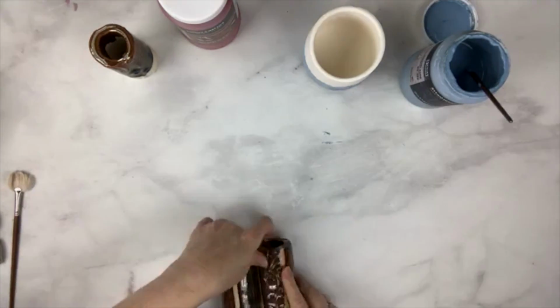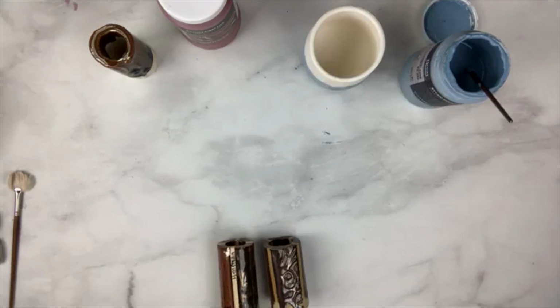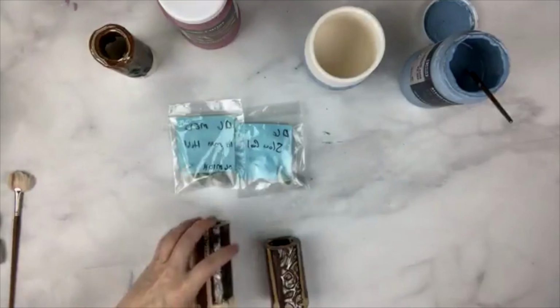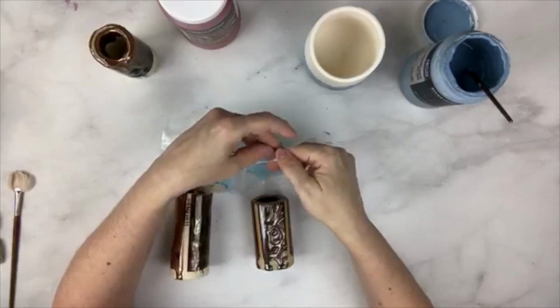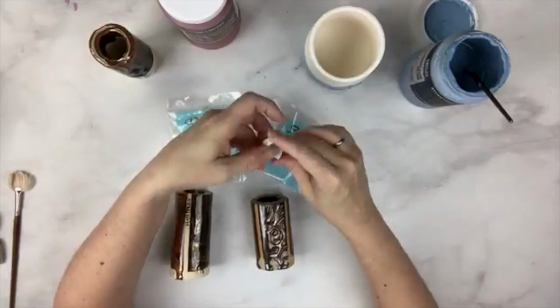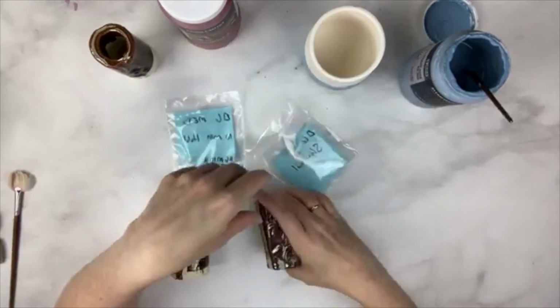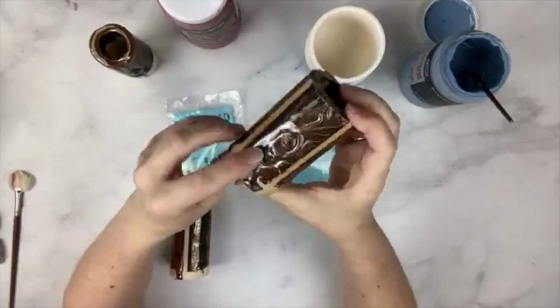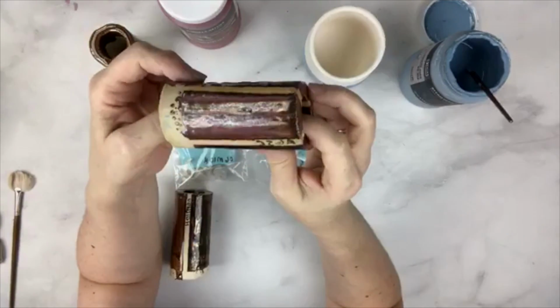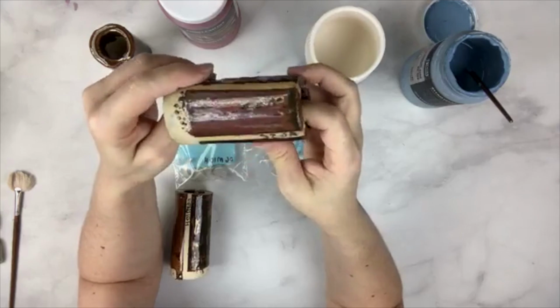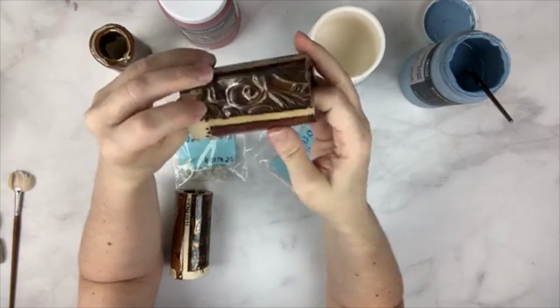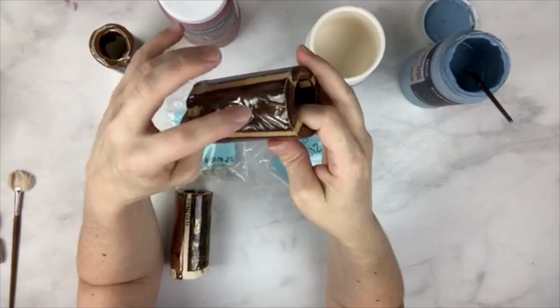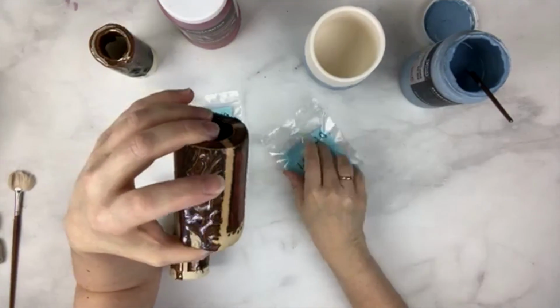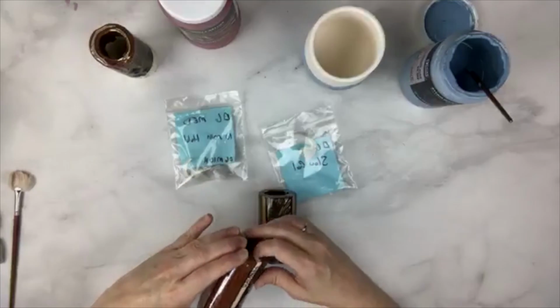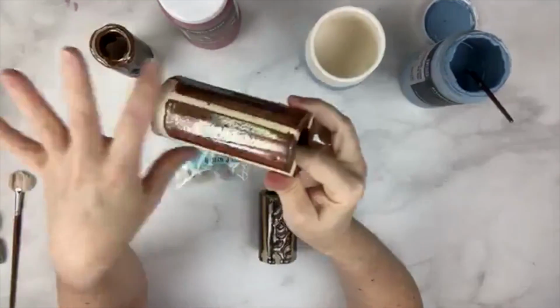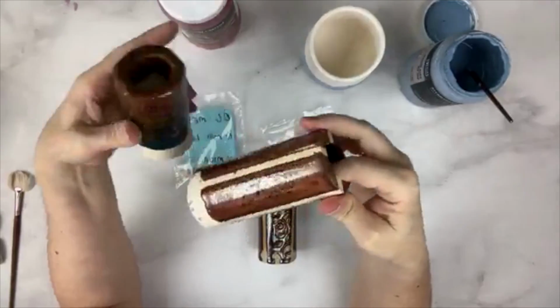So now you might be saying, well, some people say that they fire ancient copper to cone 6. So Shantae did look at a cone 6 slow cool. So this is a full cone 6 slow cool schedule, and 3 coats. Doesn't look too bad. It's got a lot of red in it, more red than you would expect, but it comes out glossy and not so dark. So the higher temperature was working, but to really get that crystal growth, the pretty kind of freckles,